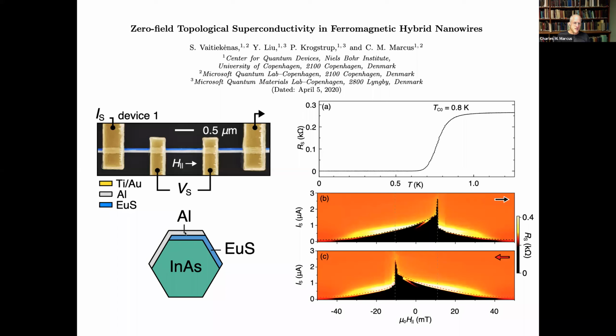How do I know that? Well, because this thing is not really protected against the Clogston limit. If it has some spin orbit from the indium arsenide, maybe, but aluminum doesn't have very much spin orbit coupling. So when the europium sulfide drives this thing close to Zeeman equals gap, it kills the superconductivity in the aluminum. It really will kill it. So there's, I think, not enough magnetic field to keep these states at zero. And maybe this is consistent with what you're saying, that the system is most of the way toward the field being enough to bring them together. But then when the field is decreased, they separate, but there's no topological transition at that point.